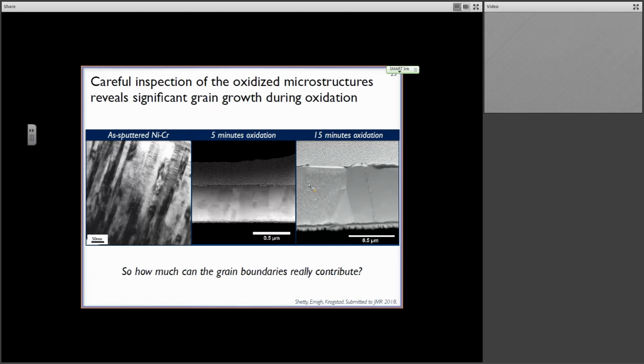So the previous slide was after a whole hour. This is the as-deposited microstructure I showed you before. If we oxidize it for 5 minutes, only 5 minutes, and it's a real 5 minutes, we didn't ramp up over an hour. We preheated the furnace, we inserted the specimen for exactly 5 minutes, and then we pulled it out and quenched it. Because it's a very small sample volume, quenching is actually realistic here.